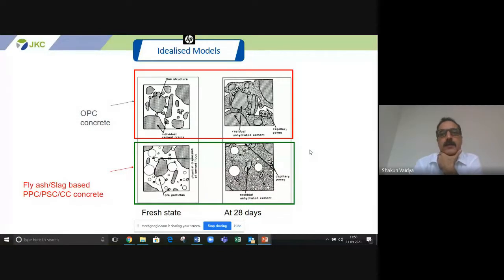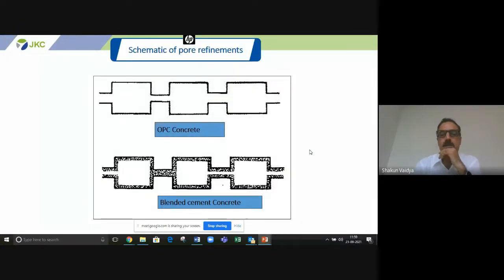So idealized models of concrete: you can see at the top OPC concrete, made with ordinary Portland cement, is much more fragmented, and you can see concrete produced with fly ash or slag based cements. Much more refinement is there, and the concrete at 28 days appears to be much more dense and impervious. So this is how typically the pore refinement should take place.